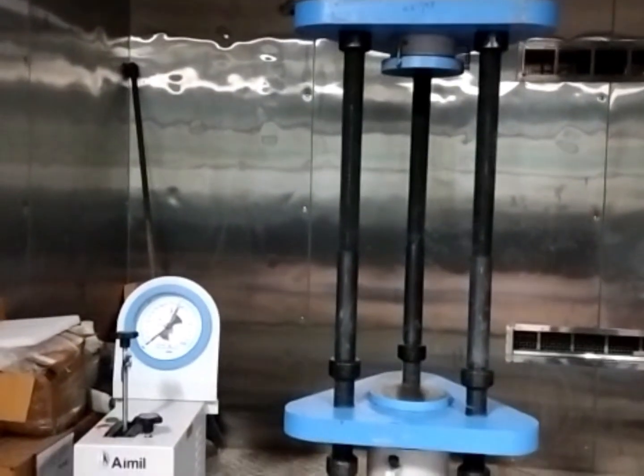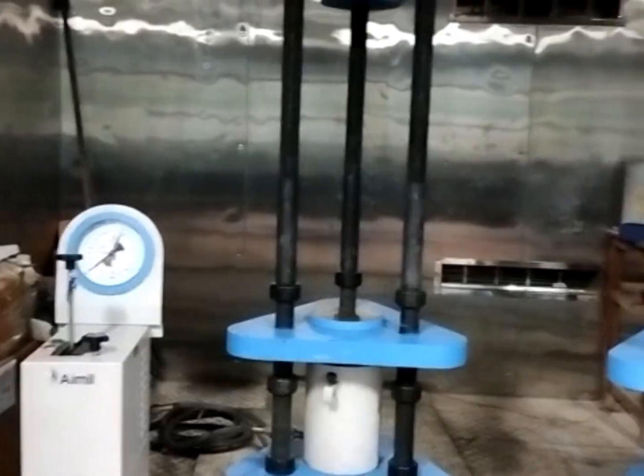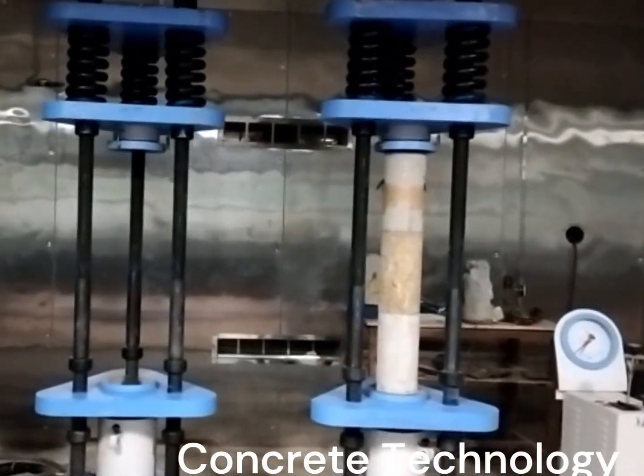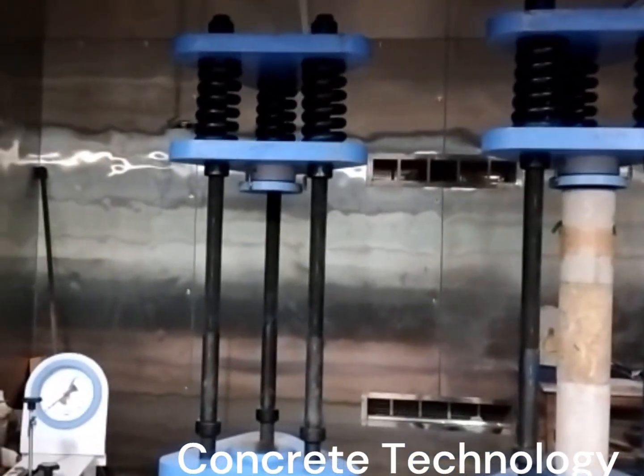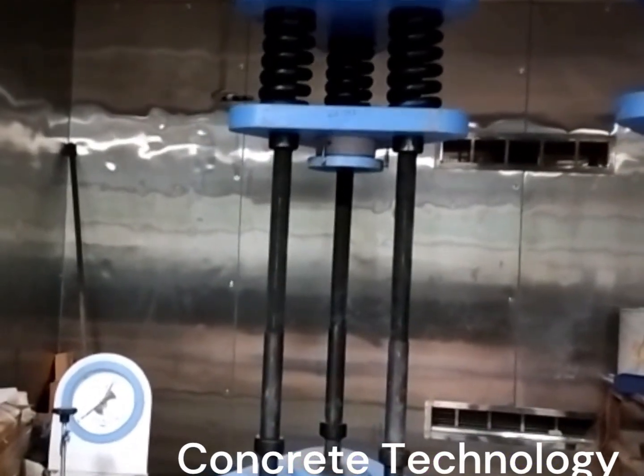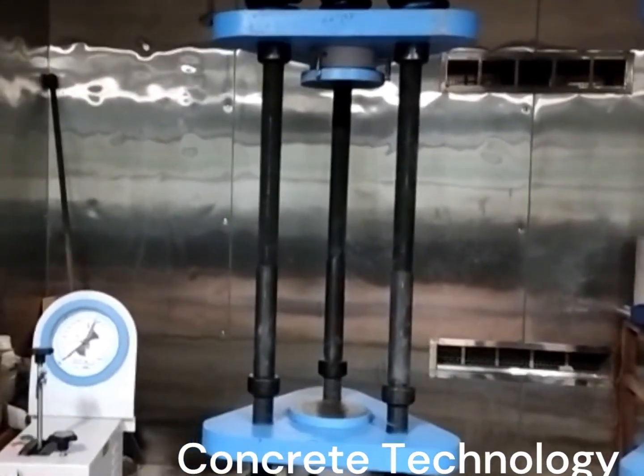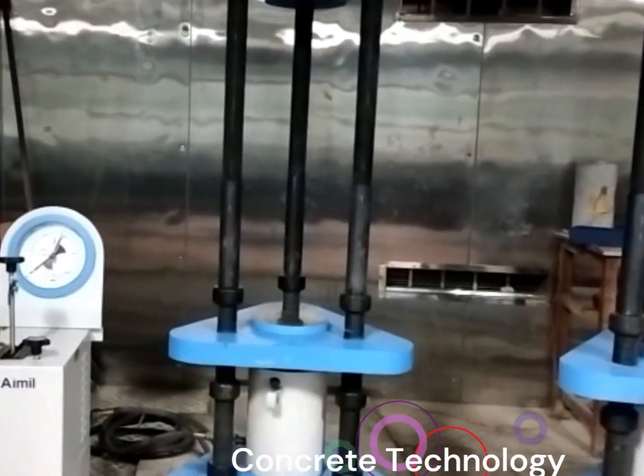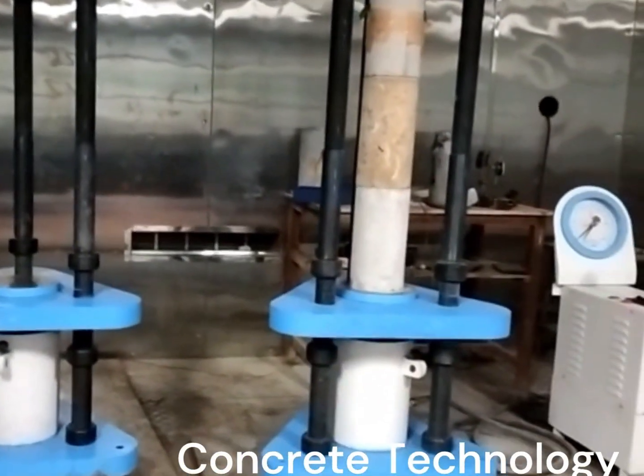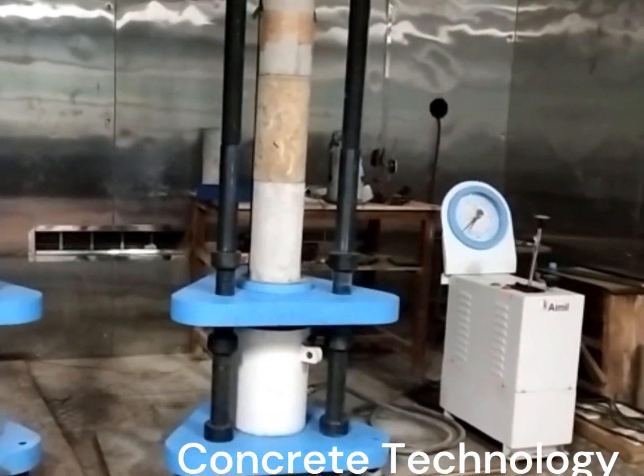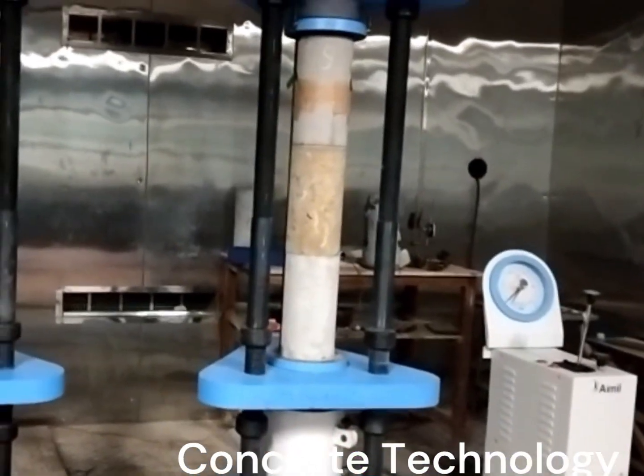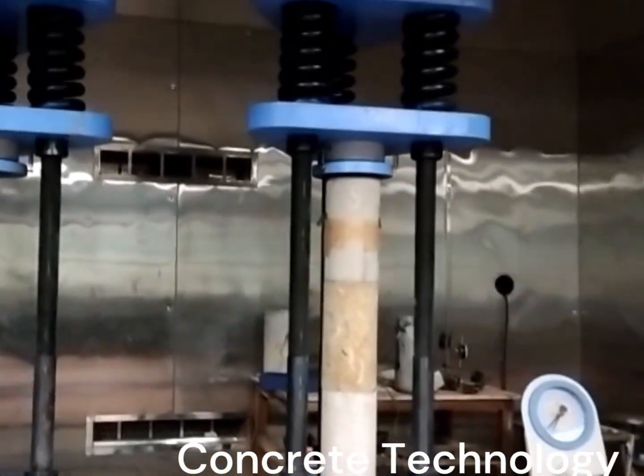The creep test rigs for concrete is required for determining the specific creep of mass concrete specimens required for evaluation of its tensile strain capacity in laboratory. Tensile strain capacity of concrete mix is essential in estimating placement temperature of mass concrete, which is an important parameter for controlling thermal cracks in mass concrete to be used during construction of hydraulic structures.